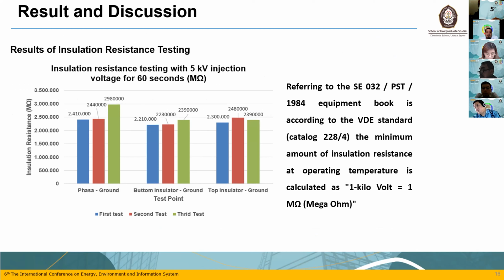In this result of insulation resistance testing, referring to the SE 032 / PST / 1984 equipment book, according to the VDE standard catalog, the minimum amount of insulation resistance at operating temperature is calculated as 1 kilovolt equal 1 mega ohm. With the result of the insulator with epoxy resin material, phase to ground, bottom insulator to ground, top insulator to ground, with result resistant insulation more than 2 million.